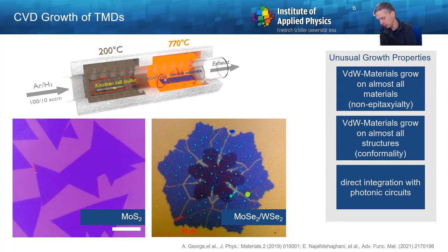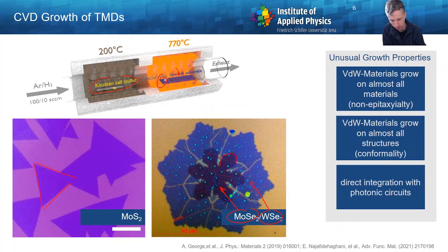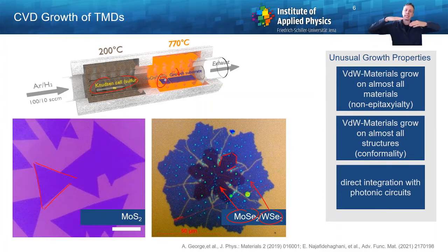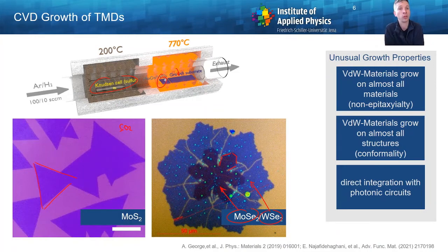An example here on the bottom left: these are monolayer crystals of molybdenum sulfide. You can also change the composition of your precursors during the growth and create heterostructures — in this case a heterostructure of molybdenum selenide in the center and tungsten selenide on the outside, where the transition edge between the two forms a p-n junction of epitaxial quality. These are all van der Waals materials, which means out of plane they bind very weakly, so they will grow on almost all materials irrespective of epitaxial compatibility — in this case on silicon dioxide, which is not crystalline at all, but you still observe crystalline growth modes.